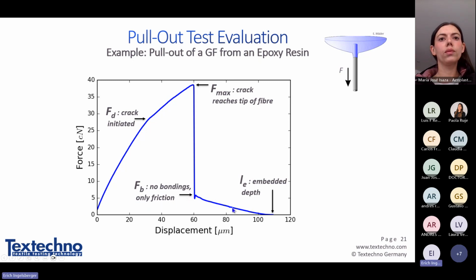If you look at this specimen here, you can see this meniscus. We have only embedded this depth, and this meniscus will be created either by increasing contact angle or by cooling down. This is unpredictable, you do not know. Therefore, to know the embedded length, you cannot rely on the depth which you defined while creating the test specimen.